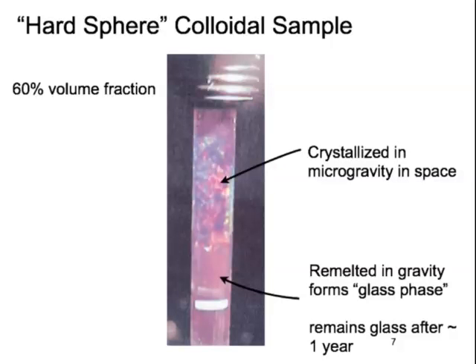This is a year after we mixed it. The magnet is still there, which means it's a glass. That is, it's something with no long-range order, but a shear modulus, a rigidity, so this thing doesn't fall through it. It's not just viscous. And above it is the crystal over here, which grew in space. And this crystal slowly grows into here, which shows you this equilibrium phase.